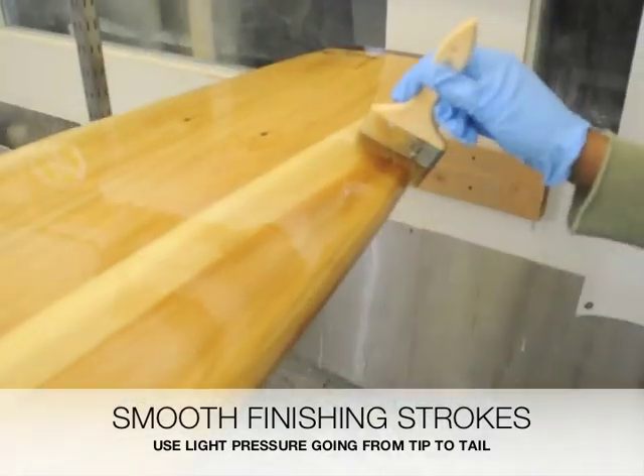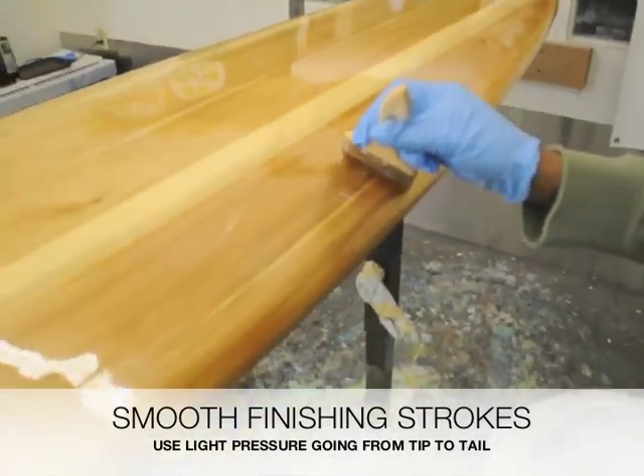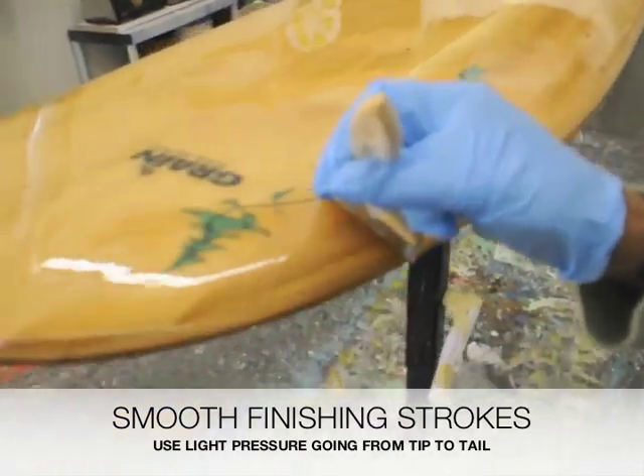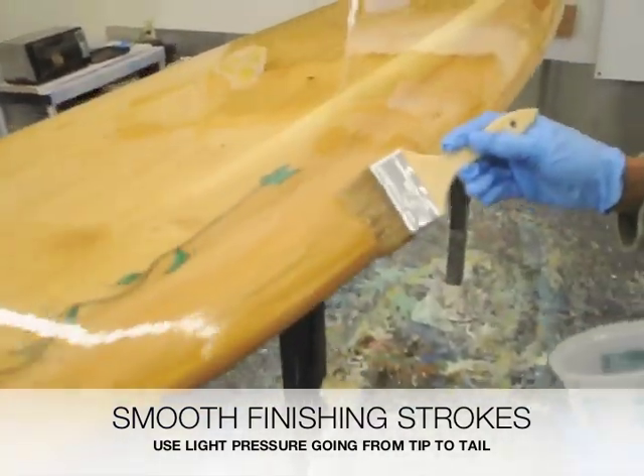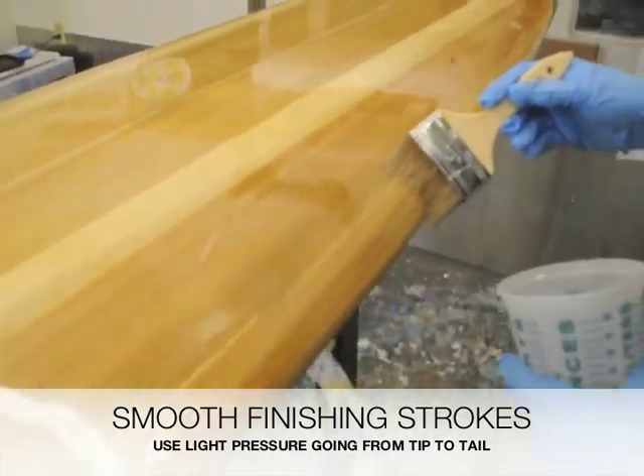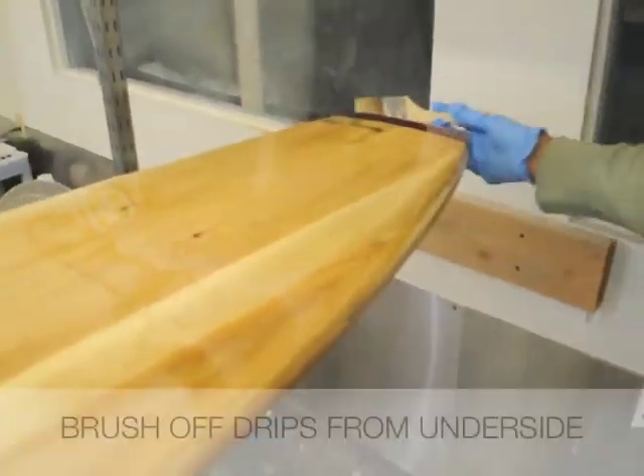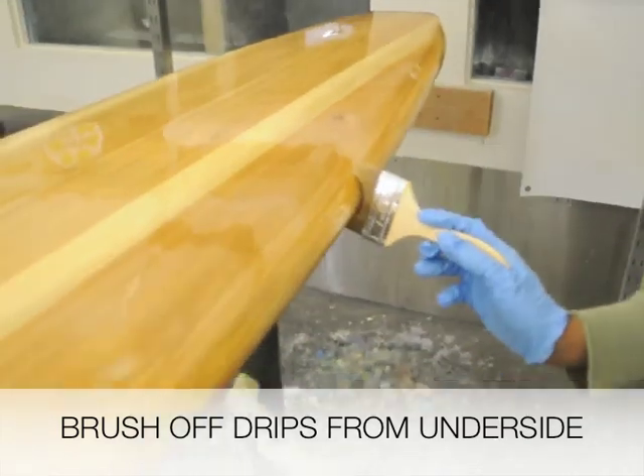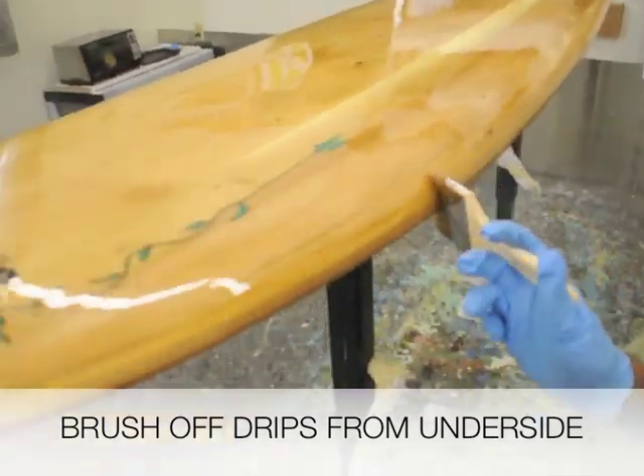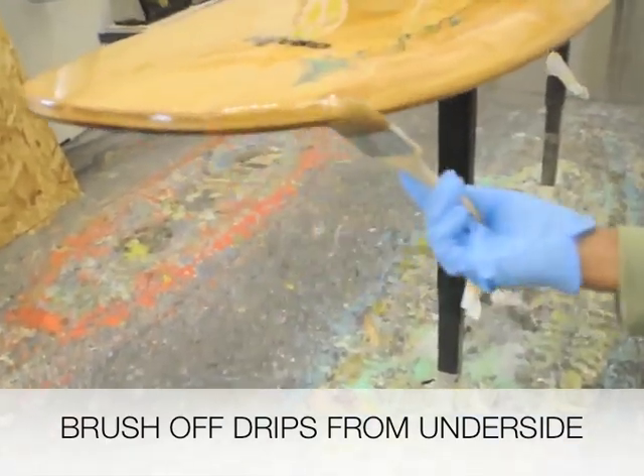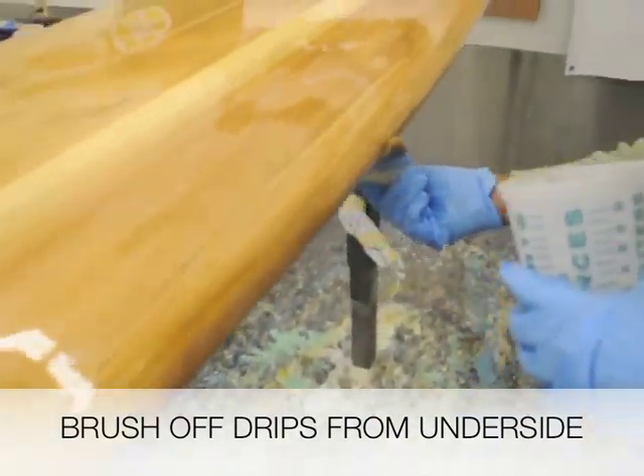Finally, using very light pressure, apply finishing strokes from tip to tail, again, working from the center of the board out toward the rails. Then, after your last brush strokes, you can go back and using a hairdryer, pop any trapped air bubbles. Then, allow the resin to self-level.